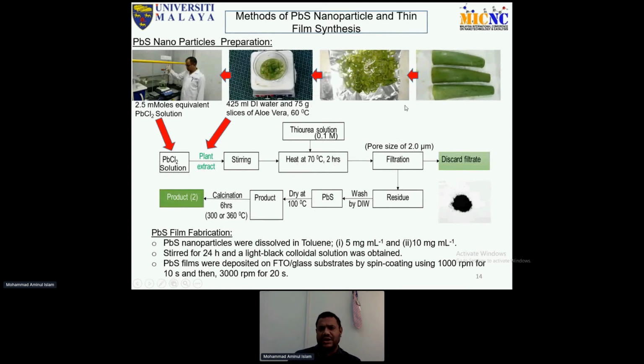We are using aloe vera, which is collected from the Hentian Kajang near the UKM, and slice it, then sink it in DI water and stir at 60 degrees centigrade. Then we collect the extract. The extract is a slightly brown extract, and then we make the lead chloride solution. Then we incorporate the extract there and stir for 10 minutes. Then we add the thiourea solution of 0.1 mole and heat at 70 degrees, stirring for 2 hours.